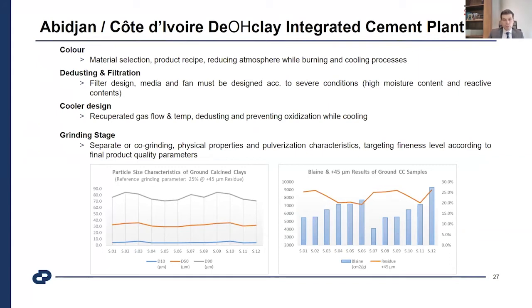Dedusting and filtration are important because we are talking about very high moisture contents and a very high amount of water vapor. The filtration systems need to be selected according to that. Cooler design is critical because not only the cooling effect, but also recuperation and heat efficiency are directly affected by that. Additionally, the oxidizing and reducing atmosphere is also related to the cooler. It's also critical to do it.